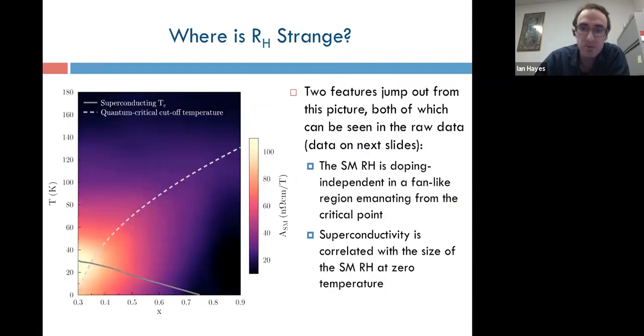This is an intensity plot for that strange metal field dependence in the doping and temperature plane. And I've started here at 30%. I've neglected the underdoped part because the transition to the antiferromagnetic phase involves reconstruction, as we heard in the last talk. And that radically changes the Hall coefficient and gives you different field dependence. So to compare apples to apples, we're going to stay on the disordered side. And there are two things I really want to draw your attention to about this phase diagram.